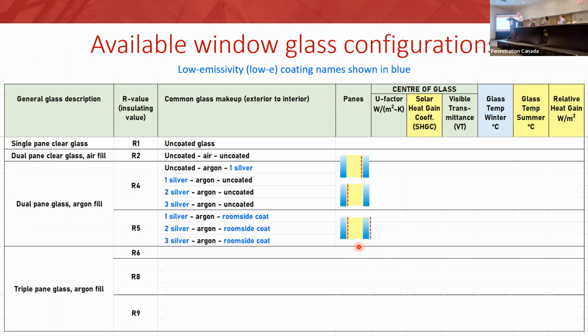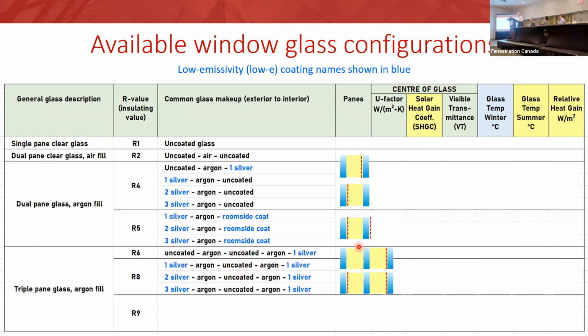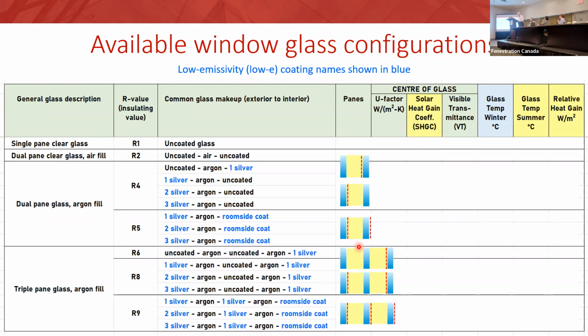So here's how our configurations stack up. I've put the pictures beside the text, and I've highlighted the low-E coatings in blue. I'm classifying them as being single silver, double silver, triple silver. That's common terminology in our industry. And I'm calling the room side coating room side coat in plain English. And so as you add more layers of glass and more coatings, you are getting higher R values, better insulation, and less heat loss.